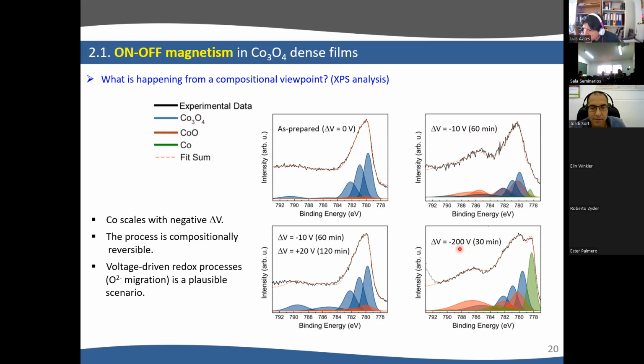If we increase the voltage to minus 200 volt, this peak from metallic cobalt becomes very obvious, as you can see here. Now, if we stop at minus 10 volt and then we apply plus 20 volt, you can see that we recover the original pattern. So basically, this seems to indicate that we are generating metallic cobalt and then oxidizing it again, depending on the polarity of the applied voltage.